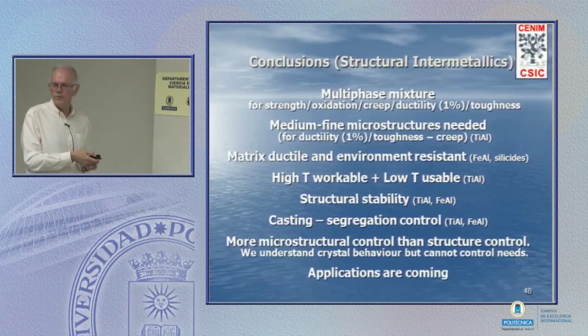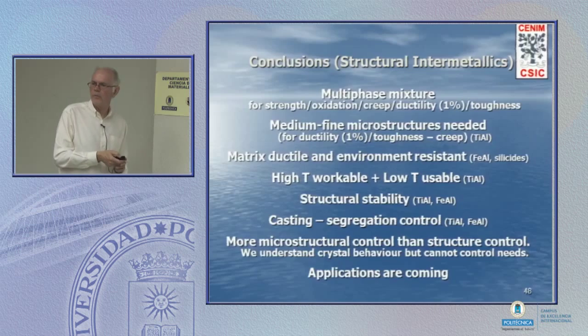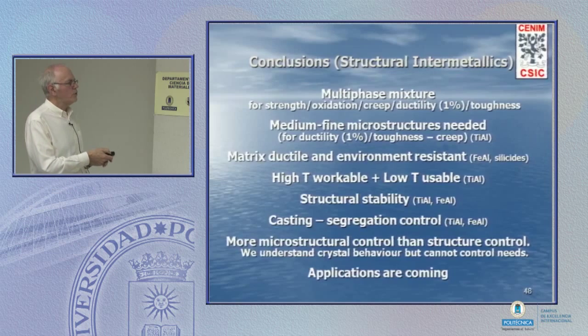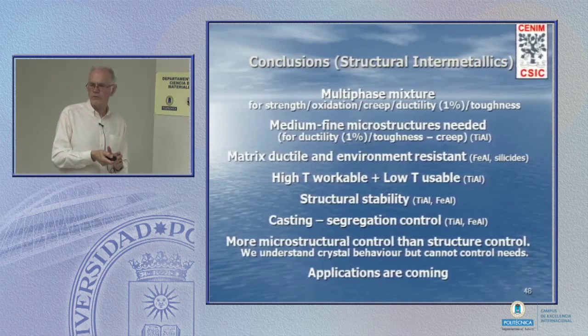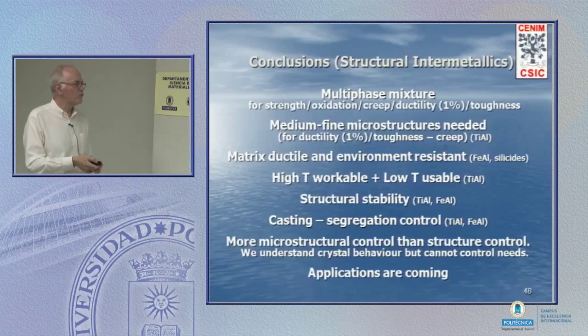Structural stability has been a problem, especially when we're looking for creep resistance, but the problems have been essentially solved. You can cast these materials, watch out for segregation. And the story has been one of composition control, but it's really been one of microstructure control. Control the mixture of phases and the size and morphology.